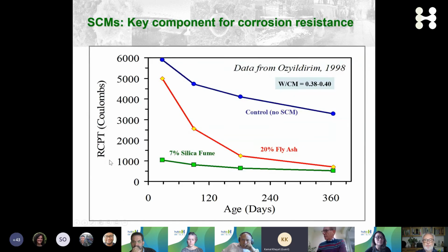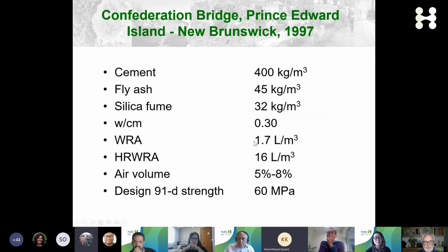And you're all familiar, I'm sure, with the rapid chloride permeability test, sometimes referred to as a Coulomb test. And here you can see some work from Virginia DOT with high performance concrete, with the use of fly ash or combined use of fly ash and silica fume. We can compare to control concrete. We can reduce quite a bit the electrical conductivity of the concrete. And this is exactly what was done when the bridge was inaugurated for the bridge deck. So this is a mixture design for what they call a C60 MPa concrete: cement, fly ash, silica fume, low water to binder ratio, a whole suite of chemical admixtures to make the concrete workable and durable.